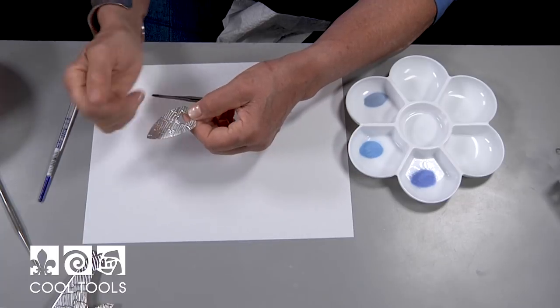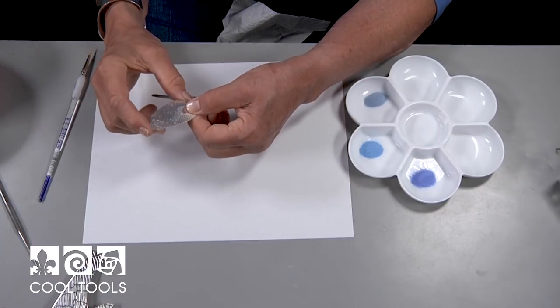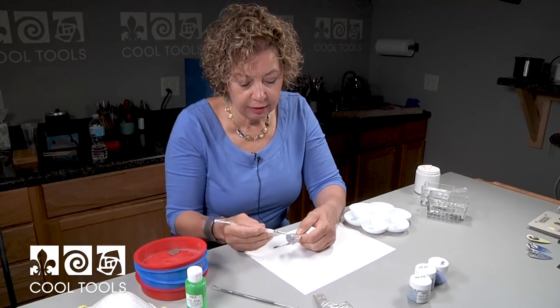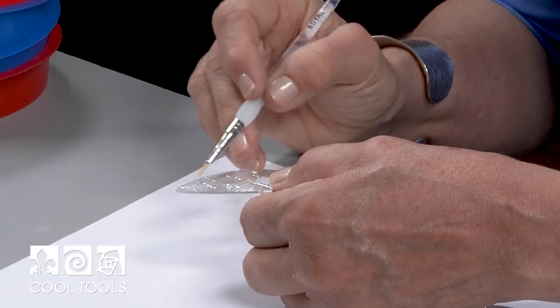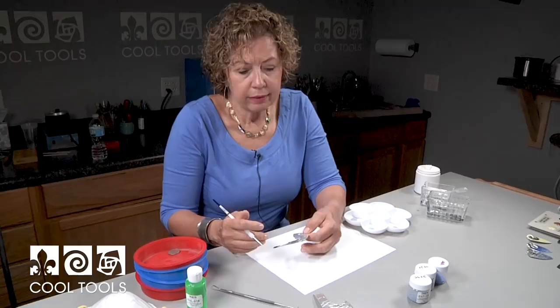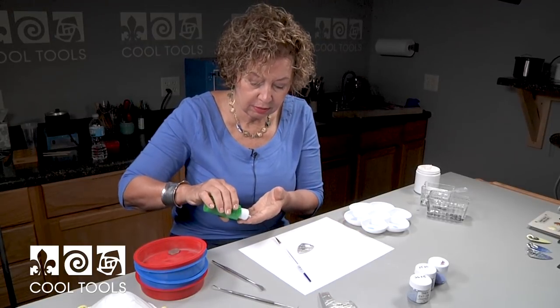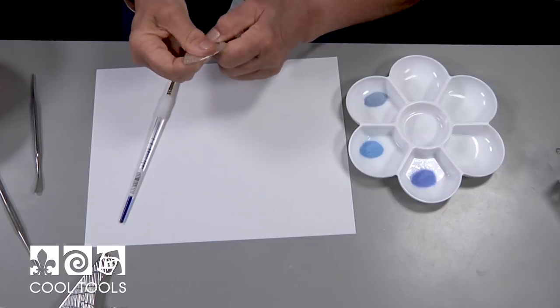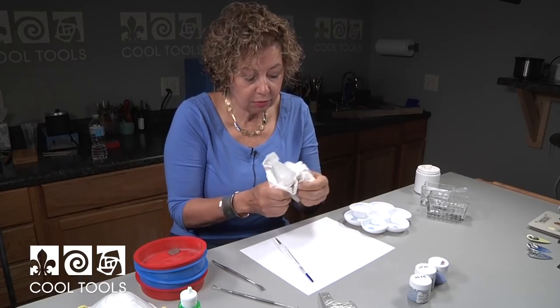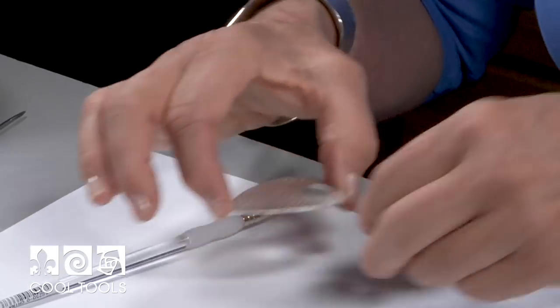I went over to the sink already and used the fiberglass brush. I've degreased this so my little grains of glass are going to go down into these recessed areas. I'm kind of lazy with some things — I'm not going to spend a lot of time trying to get the enamel off that raised surface because eventually when I get enough enamel in these recesses I'm going to stone the top down. Once again I'm going to put a surfactant on the piece because when I wet pack it has a little bit of water in it, and water and metal will bond together better if we don't have any pooling. Just a whisper of surfactant on there — so this piece is ready to go.